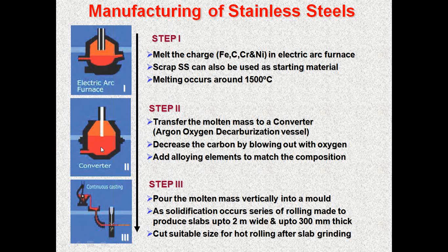Then in step 2, this is transferred to a converter where the argon oxygen decarburization process is used to decrease the carbon by blowing with oxygen, and then alloying elements are adjusted in order to match the composition. Then in the third step, the molten mass is poured into a mold, and then you make a billet or whatever you want, a cast structure, a rod structure.